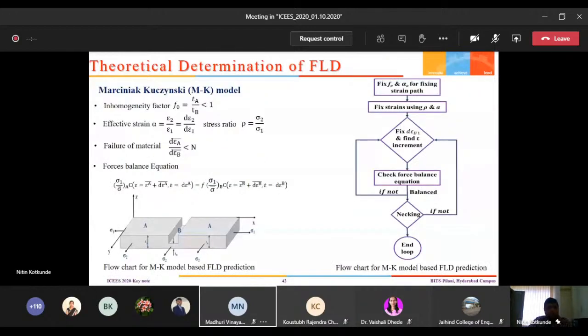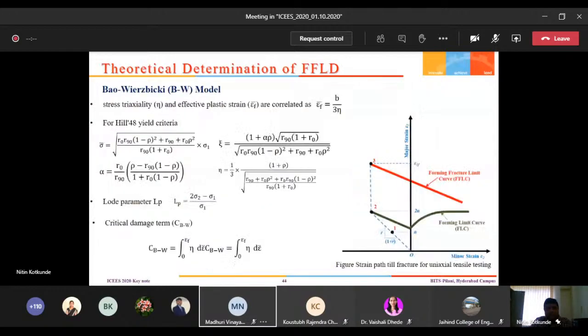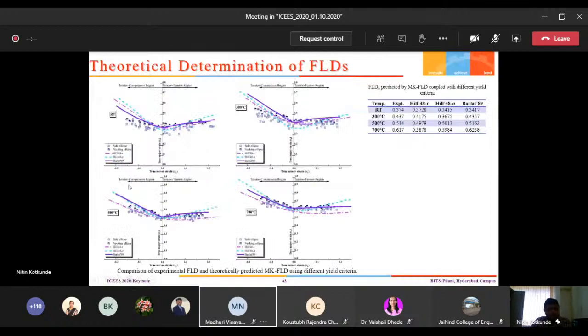simulation. So we have used the MK model, which is a very extensively used tool to determine the FLDs theoretically, so that rigorous experiments need not be conducted. So we have conducted the MK model. The input for the MK model is the constitutive models and yield criteria, whatever we have developed. So almost we have developed 7-8 constitutive models and 4 yield criteria. So this combination input we have given here for the FLD predictions, and based on that we realize that the Hill extension with JCZA model predicts the forming limit very well for Inconel 718 material.